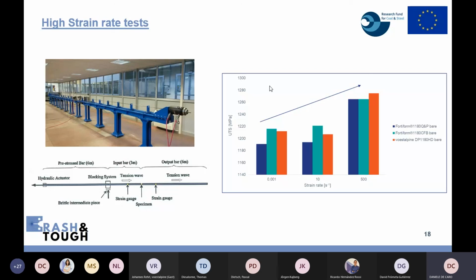Moreover, on all the materials we performed high strain rate tensile tests using the Hopkinson bar based in our laboratory in Turin at CRF. These are quite common tests that we perform to assess the crashworthiness behavior of the material at sample level. And this data has been used as input by our partners for high strain rate simulation. The results show that the ultimate tensile strength of the material generally slightly increases with the strain rate, which means that the material can sustain more energy during a crash event. That is good news.